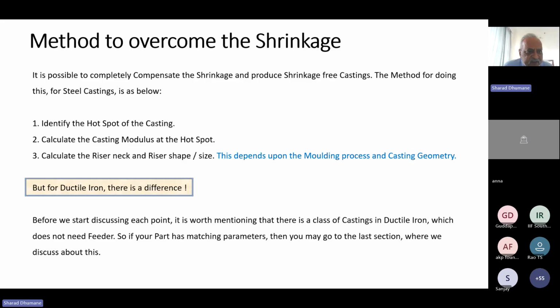And then the third stage is to calculate the riser neck or the riser shape. This depends upon the molding process and the casting geometry. So for materials like steel, stainless steel, aluminum, bronze, or copper alloys, I think this is a fairly structured and, I would say, effective method. It has a mathematical basis. So if you are using simulation software or simulation tools or a modulus calculator, you can do this work very correctly.